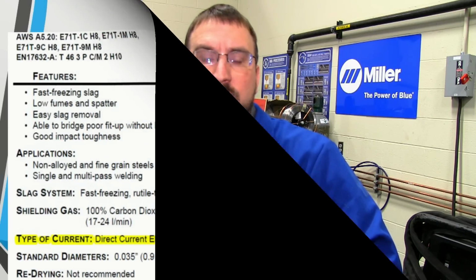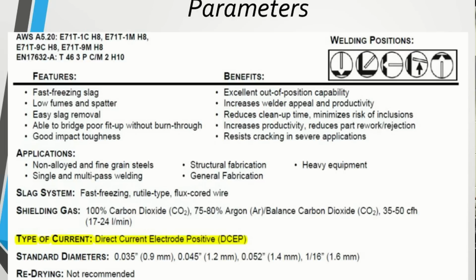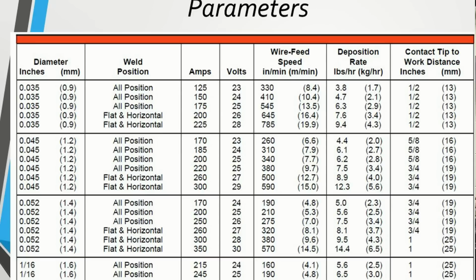So here is an example of a data sheet that tells us everything we need to know to get started using this wire. The first thing we'll look at is what type of current it requires, and in this case it's DC electrode positive, or reverse polarity. Then we'll look at the welding parameters. We'll look at what size wire we're using. We're using an .045 wire. So we'll follow that over, and there's a whole list of different types of welding parameters to use, whether we're in position or out of position. We can see the voltage, the amperage, and the wire feed speed. And then on the very end, we'll also see the correct contact tip to work distance, otherwise known as the electrical stick out. This is a very important parameter that we'll talk more about here in just a few minutes.